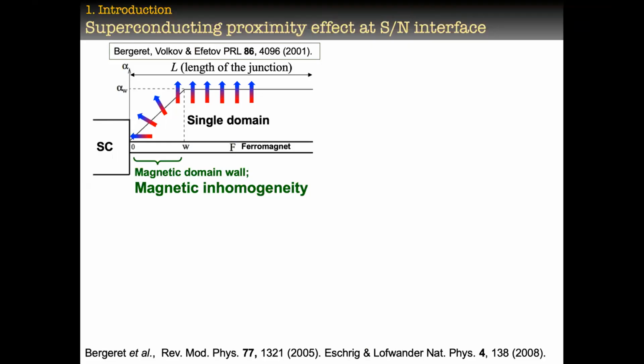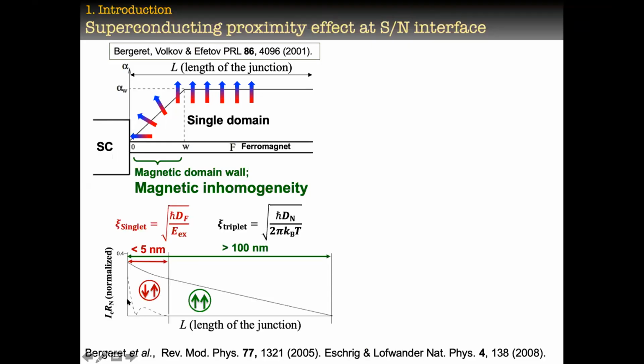So if we would have this kind of a condition, first of all, we will have this short range proximity effect, meaning the induction of superconductivity in the ferromagnet. What this broken rotational symmetry of the ferromagnet at the interface will do is convert your spin singlet Cooper pair into a spin triplet Cooper pair. Spin triplet Cooper pair means again the spin polarized Cooper pairs. And then now the spins of the Cooper pair are aligned, meaning that the ferromagnet is a friend, not an enemy anymore. And in that case, we will have a longer induction, just like it was happening in normal metals. So this is a very good thing.